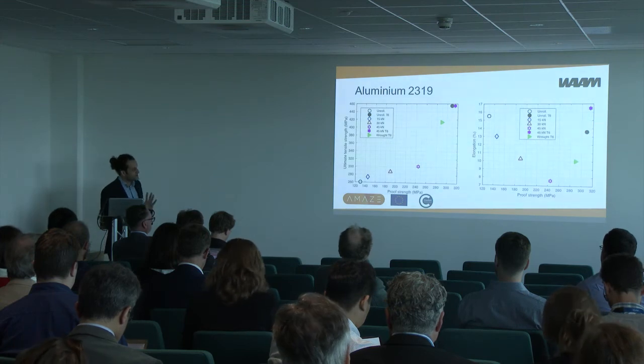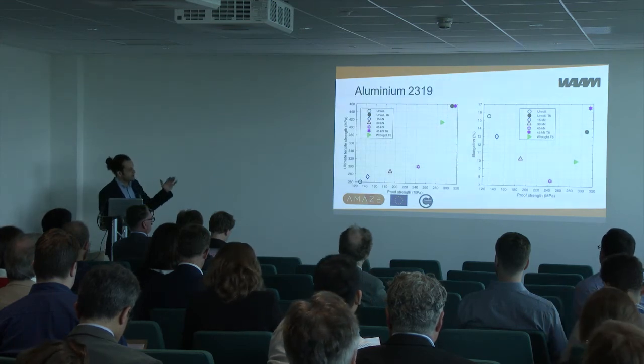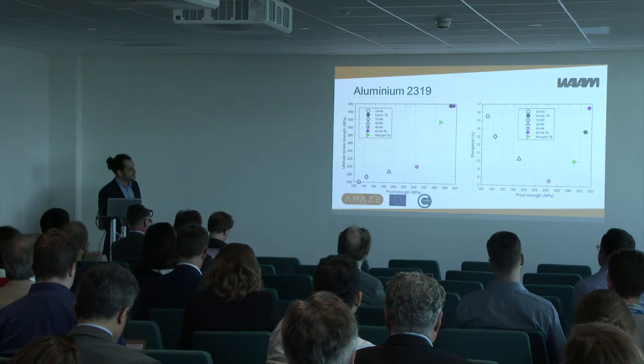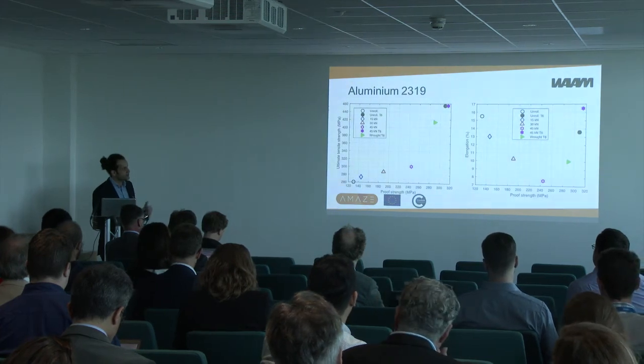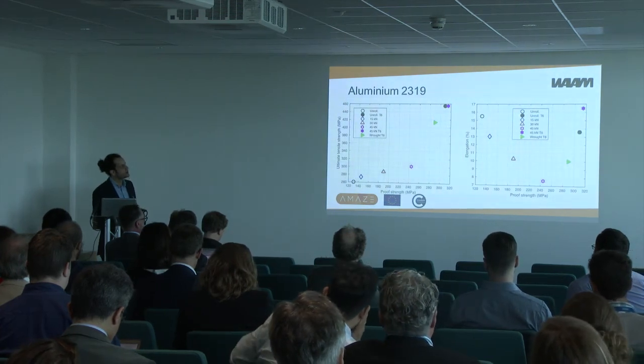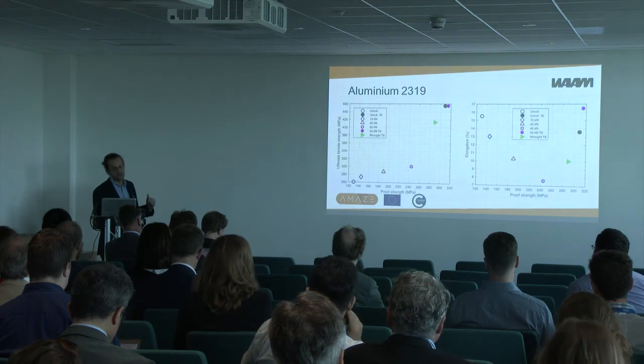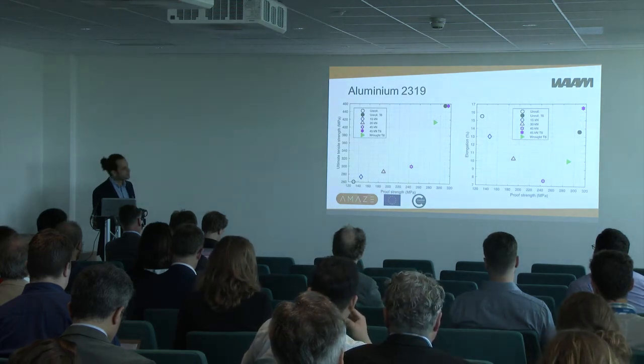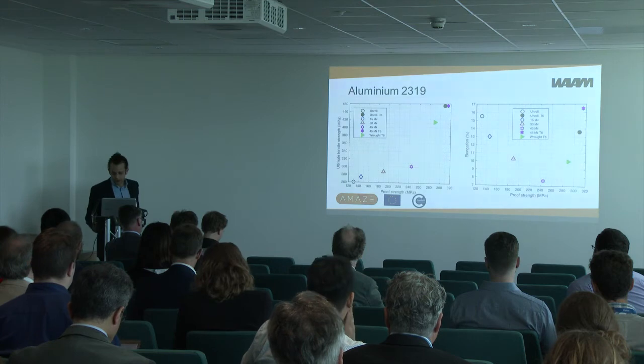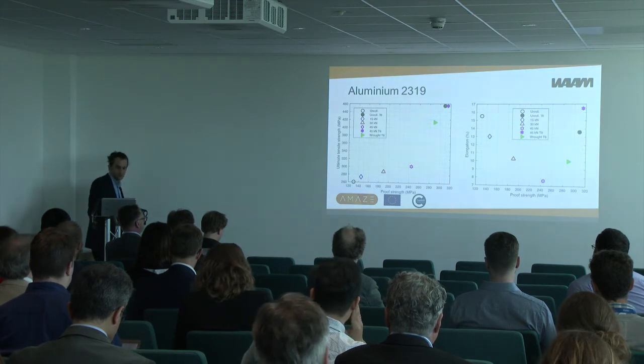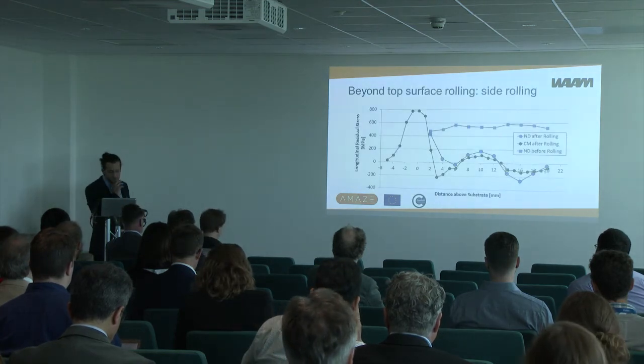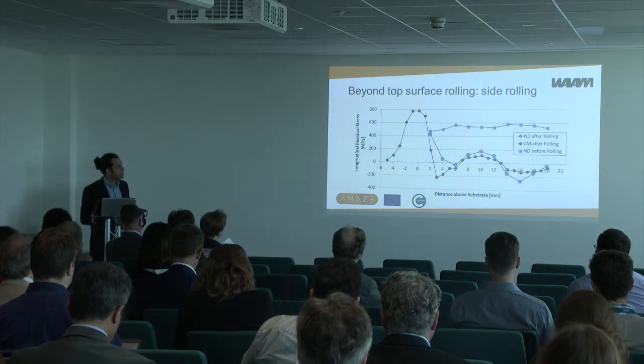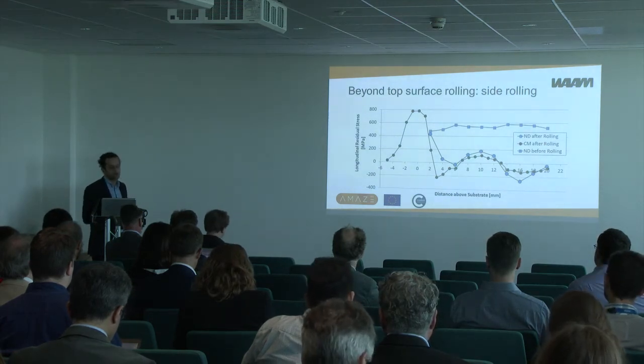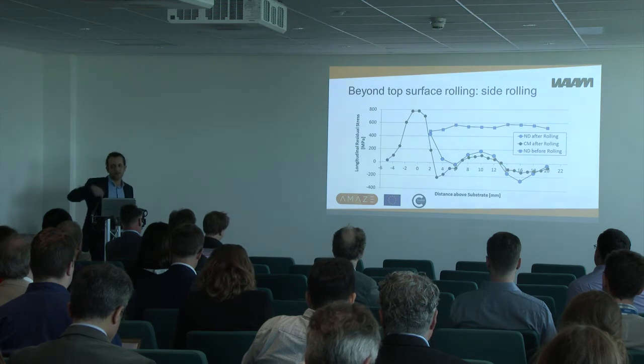2319, a very similar behavior, however, much less effect on the UTS in terms of addition of the rolling, and similarly to the previous case, we get properties that are much better than the wrought alloy, but with the temper. So I'm going to tell you what we can do to avoid the heat treatments in the next few slides.